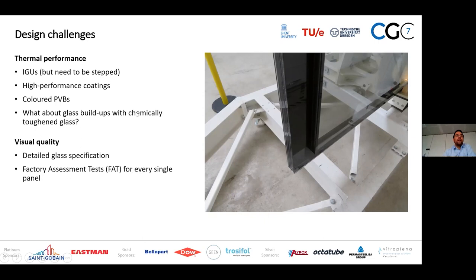To reduce G value, you can use high-performance coatings and colored PVBs. But obviously, when you have chemically toughened glass, no coatings are allowed by default due to the thin compression zone of the glass. So we simply add an annealed glass, which has decorative purposes, and it has also a coating there. As I've mentioned, visual quality is very important. So we need to develop a bespoke specification, much more tight than in architectural industry. And at the end, we need to inspect one by one every single panel to make sure that it can meet these requirements.